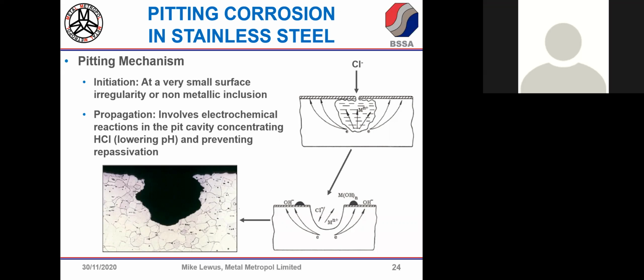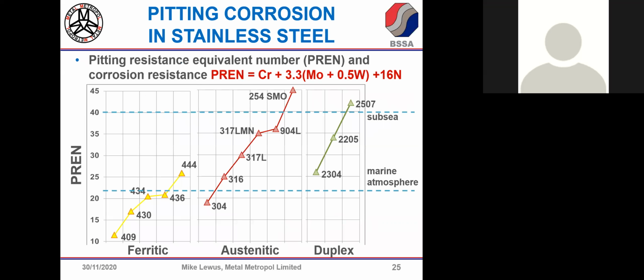So chloride and pitting in stainless steel is quite a prevalent thing, unless you choose a grade that's particularly resistant to it. Now, this next slide just identifies something we call the PREN number, or the pitting resistance equivalent number. The bottom line is the higher that number, the more resistant to pitting the stainless steel grade is. As a fairly arbitrary rule, if the PREN number is above about 22-ish, you're in a reasonable position for exposure to the atmosphere.